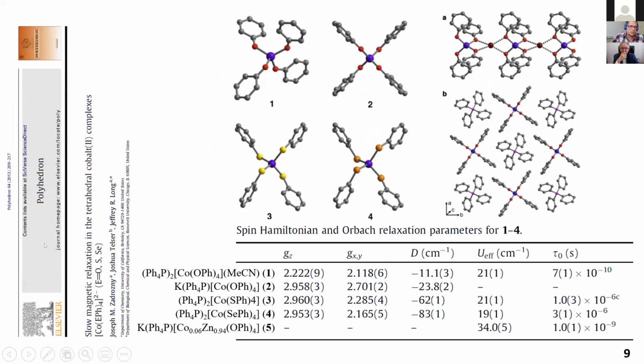One more work described tetrahedral complexes of cobalt with phenyl chalcogenate ligands with oxygen, sulfur, and selenium donor atoms. All of them demonstrate slow magnetic relaxation in zero field, and the zero field splitting parameter for all these cobalt compounds is very sensitive to the donor atom of the ligand, as exemplified by a significant decrease in D value along an isostructural series.